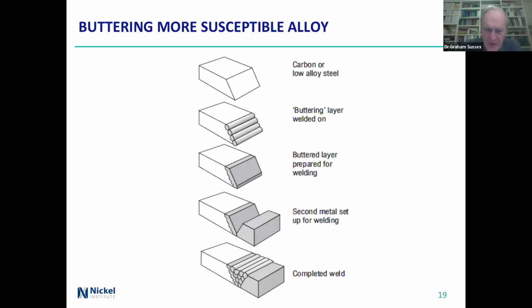The second metal set, which is in the buttered layer, is that. The reason why it works is because you're not having a large amount of heat in, so you're not getting a lot of the carbon or low alloy steel in this case into the actual weld zone. It's basically the same as doing a weld overlay.